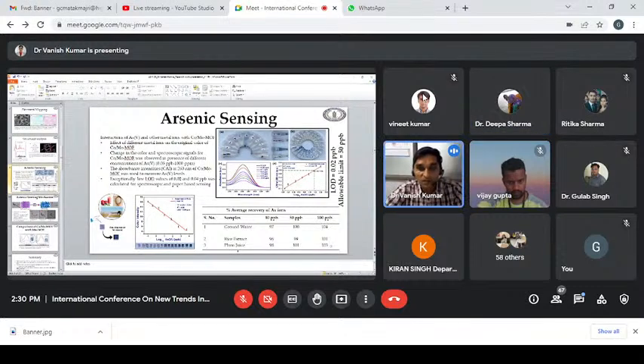Anyways, the groundwater was already having 1.1 ppb of arsenic. Likewise, rice extract was already having 0.08 ppb of arsenic, and plum juice was already having 0.3 ppb of arsenic, which was excellently sensed by our sensor. Then we further spiked those samples with known concentrations of arsenic ions, and those signals were again consistent with ICP-MS. As I mentioned earlier, ICP-MS is the gold standard for measuring the levels of these contaminants in diverse samples.